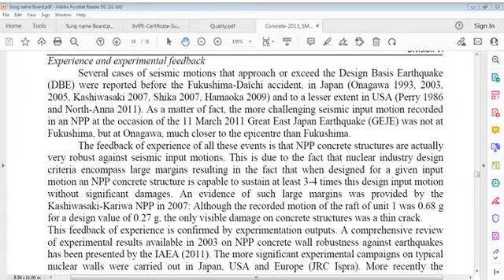Evidence of such large margin was provided by Kashiwazaki, Japan, NPP in 2007, although recorded motion of raft of Unit 1 was 0.68 G for a design value of 0.27 G. Only visible damage on concrete structure was a thin crack.